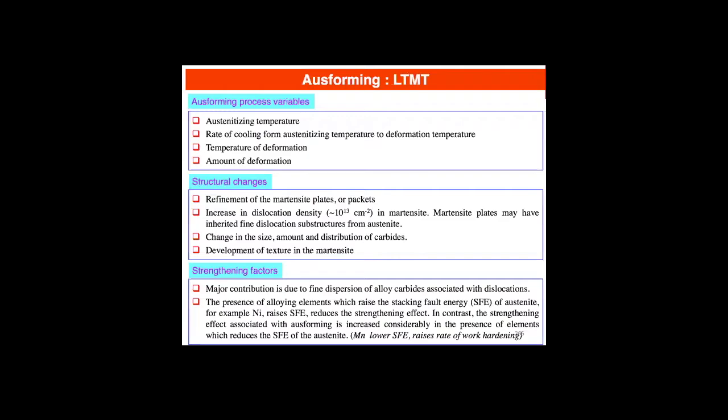carbides, right? So much of what we talked about with aluminum is really also critical to steel, right? We're coming up with different strategies to get these fine dispersions, either through quench and tempering, through secondary hardening of alloy steels, or through controlled thermomechanical processes, right? We want a martensite structure with fine carbides that we can then temper to get back some of